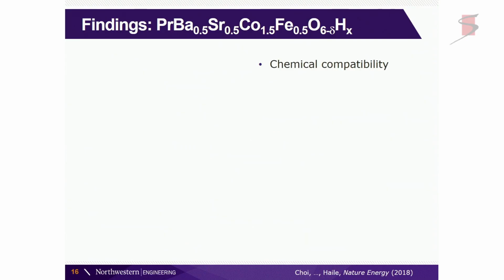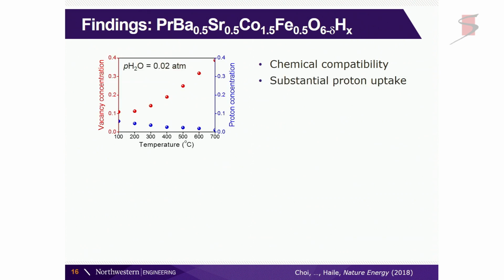But all right, so this is our new cathode material that we decided to use for this system. And we first made sure that it was chemically compatible with our electrolyte. And after seeing that, we established that it has a lot of proton uptake, which is useful for getting the species through it. So we could see that the proton concentration is reasonable at the temperatures that we wish to operate. And just to show you that it is also less than the total oxygen content, so we're not overfilling the sites.